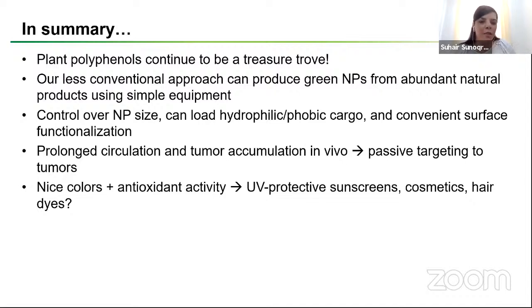projects, we were able to achieve different types or different sizes of the nanoparticles. We showed that we can load hydrophilic drugs and hydrophobic drugs. We can modify the surface with polyethylene glycol, and likewise, we can potentially add other surface ligands. Our in vivo studies showed they can achieve prolonged circulation and tumor accumulation with passive targeting ability. And also, especially for the nanoparticles from coffee, they have nice colors and their antioxidant activity. So they open the way for applications in sunscreens or cosmetics, or maybe for example, for hair dyes, like an organic alternative to the conventional hair dyes.